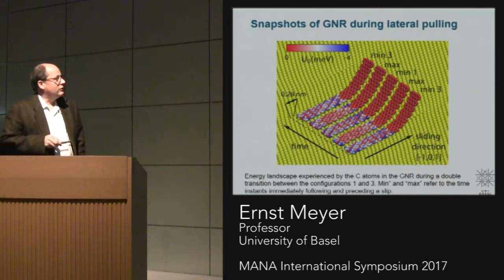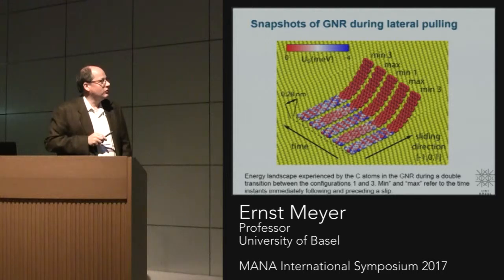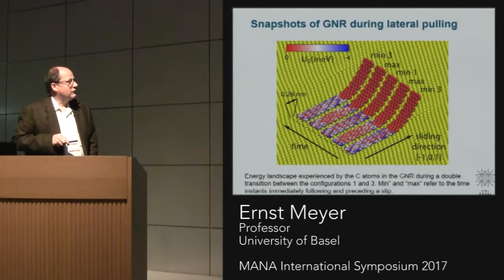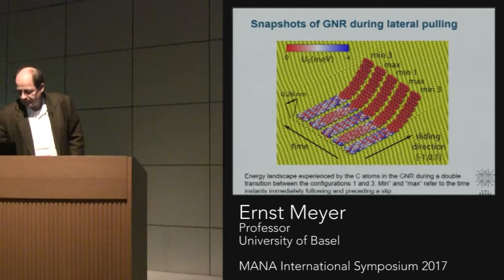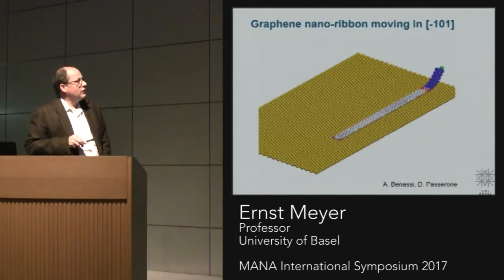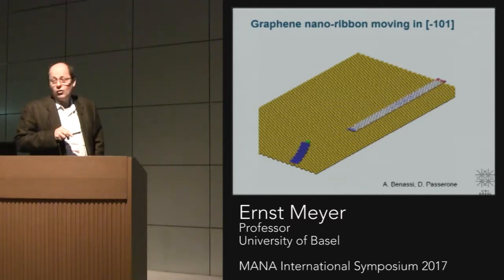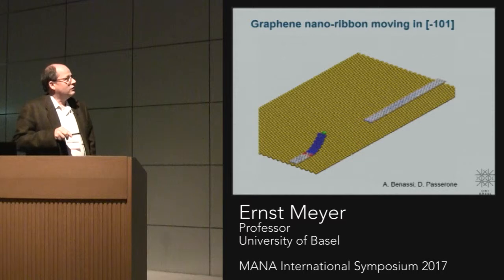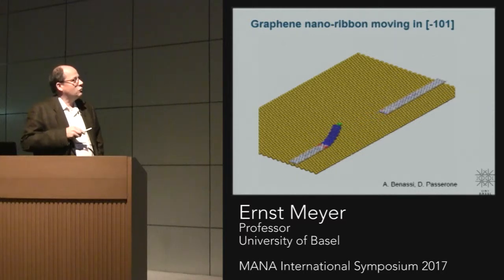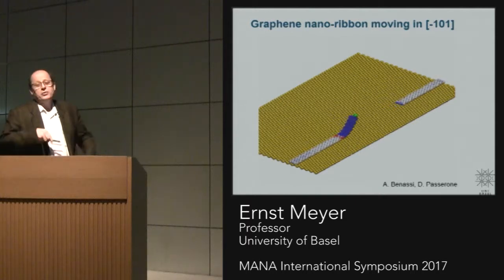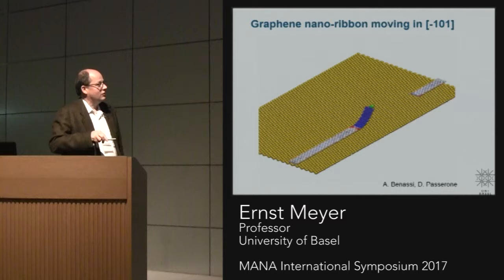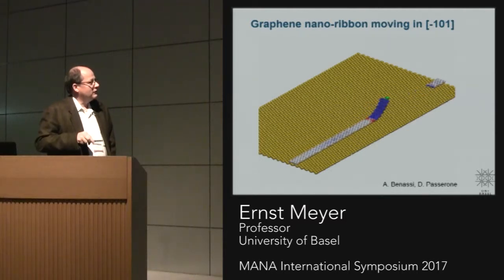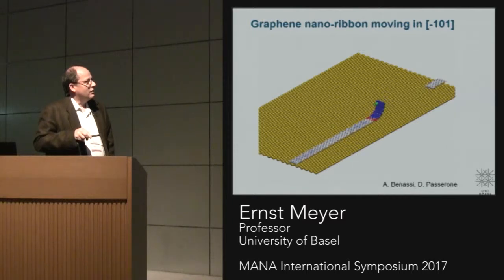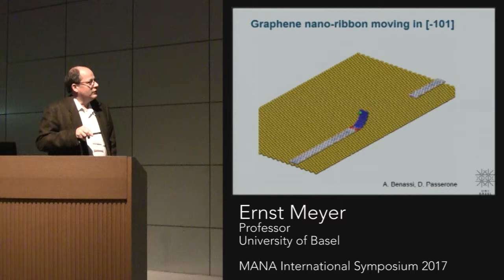But it's also here, this is a small one, which shows that shortly before the slip, or before the movement of these little wires, you see that the most attractive energy, the largest forces, are at the boundary or at the border here. So here's now a little movie of the ribbon moving in the -101 direction, and you see that along the ribbon there's not much structure to see, but at the end, so it's periodically repeated, that's why it's entering on the lower side again. But now here you see it again, so basically the biggest effect is actually here at a detachment point, and also at the end.